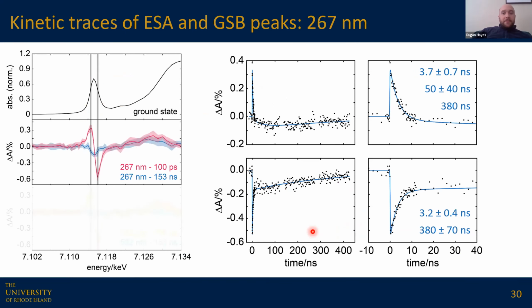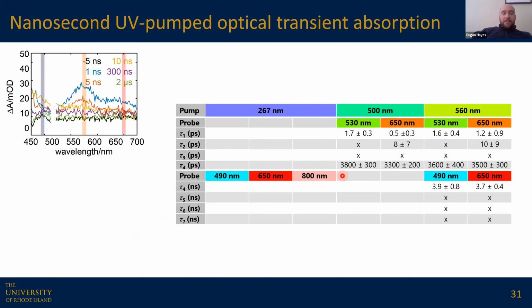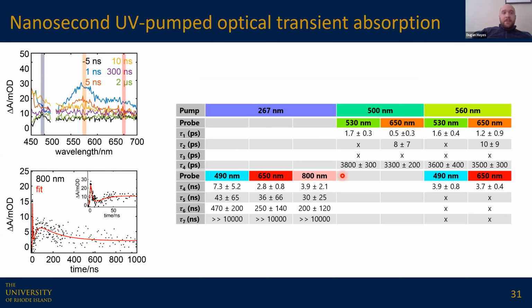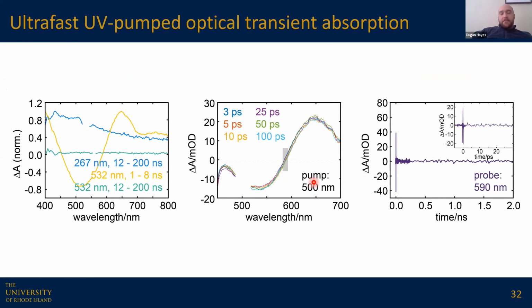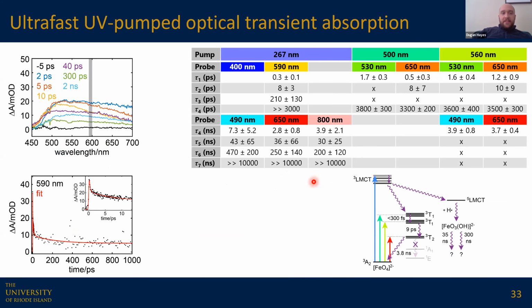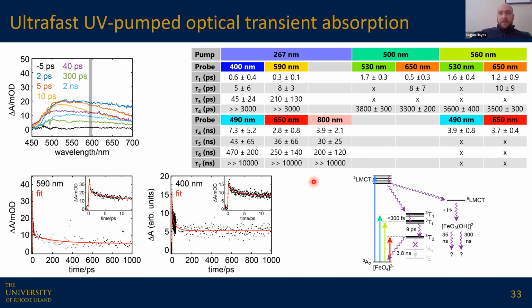We then, of course, have to complete the photochemical side where we're making this metastable iron 5 species following UV excitation. This is challenging because most of the initial triplet LMCT goes through internal conversion, but we're able to see some additional time components here and compare that to our long time data, and then follow this up with pretty exhaustive optical transient absorption in the nanosecond pumping across the visible absorption, and then through some more detailed analysis of our ultra-fast UV excitation, we're able to figure out the branching ratio between these two pathways. And I'd be happy to talk about that in more detail if people are interested.